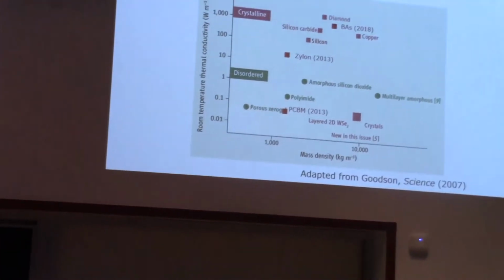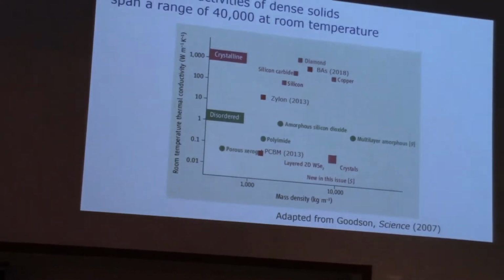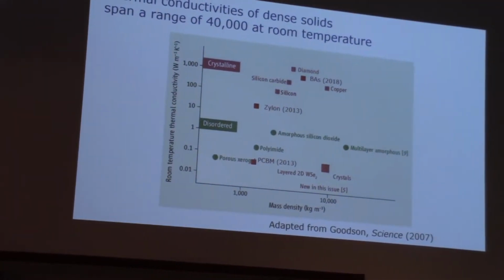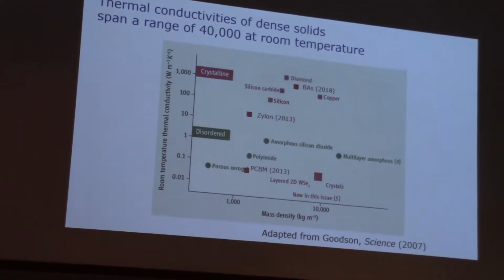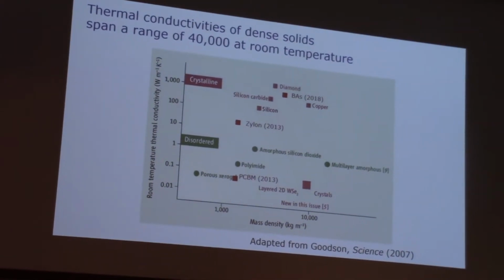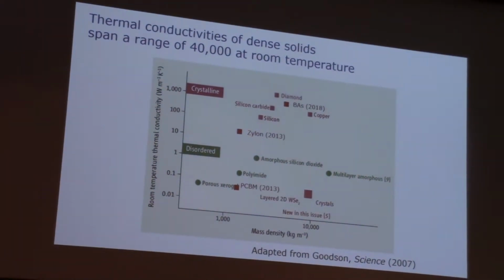Here's an interesting data point which comes from 2018. There were three papers in Science back to back, all reporting the thermal conductivity of the zinc blende crystal boron arsenide, all grown by basically the same technique, all measured by the same basic technique, time domain thermal reflectance.